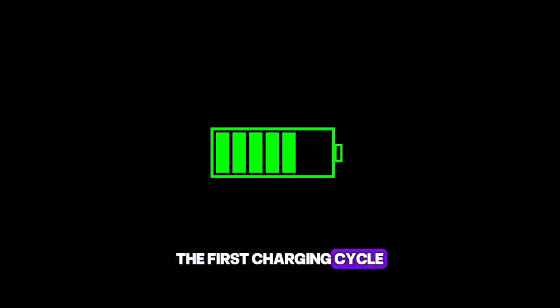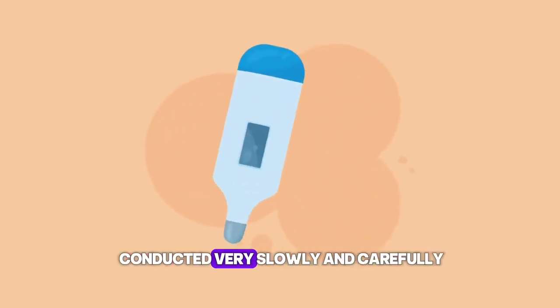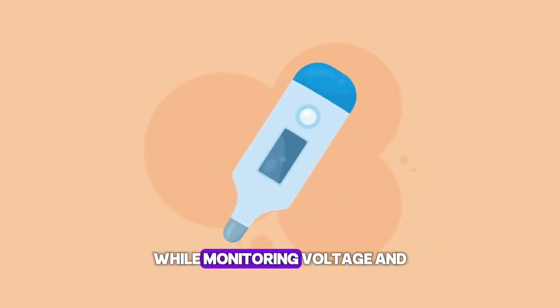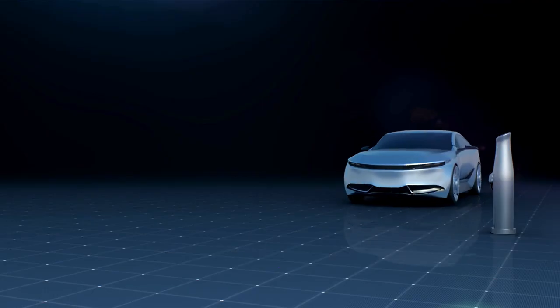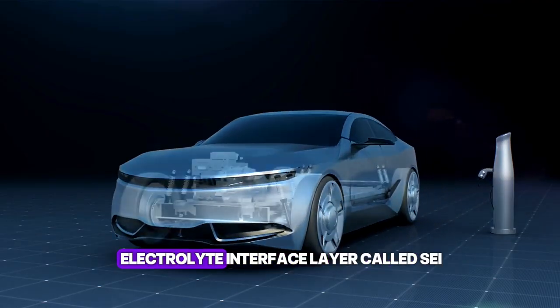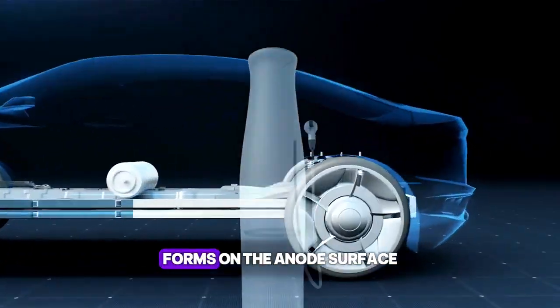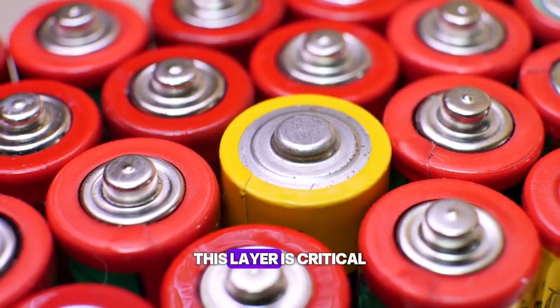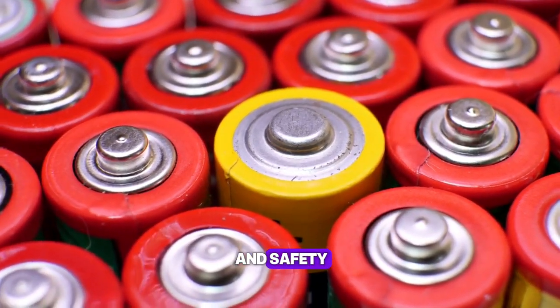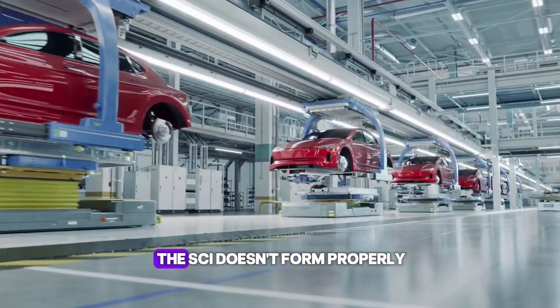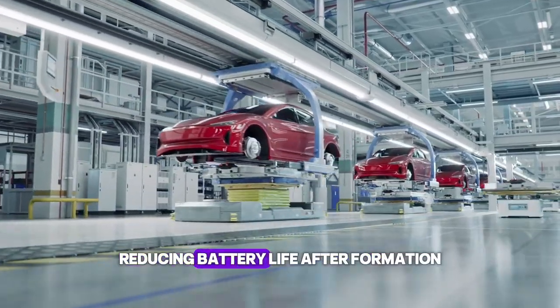The sealed cell then undergoes formation, the first charging cycle. This initial charge is conducted very slowly and carefully, while monitoring voltage and temperature continuously. During formation, a solid electrolyte interface layer, called SEI, forms on the anode surface. This layer is critical for long-term performance and safety. If formation is rushed, the SEI doesn't form properly, reducing battery life.